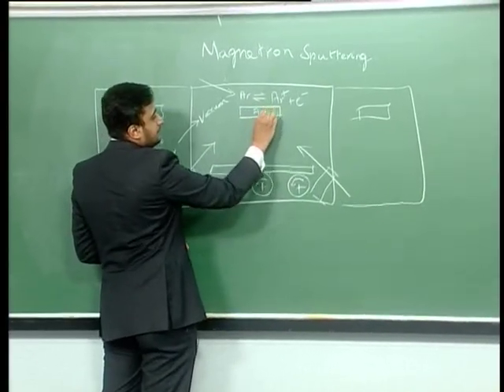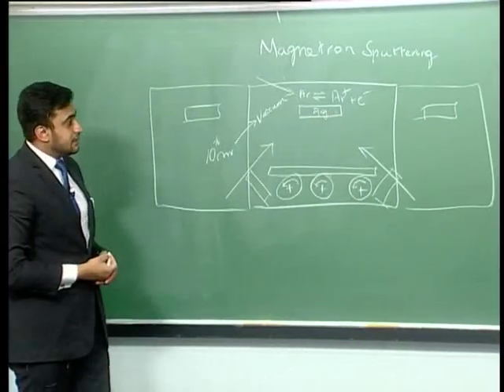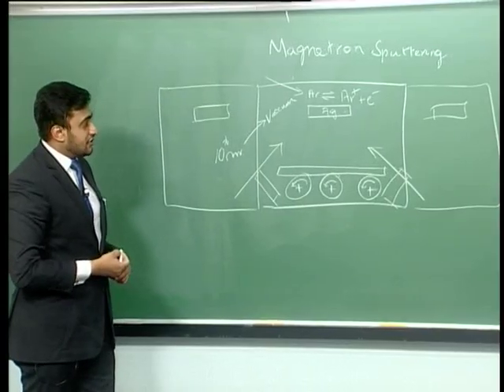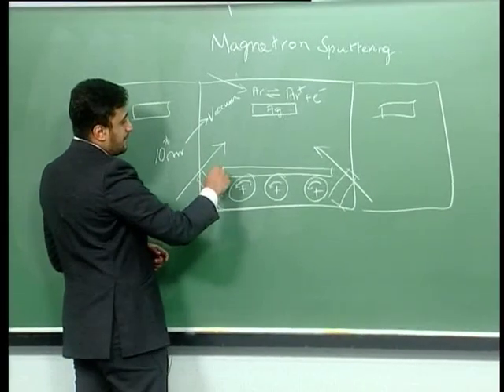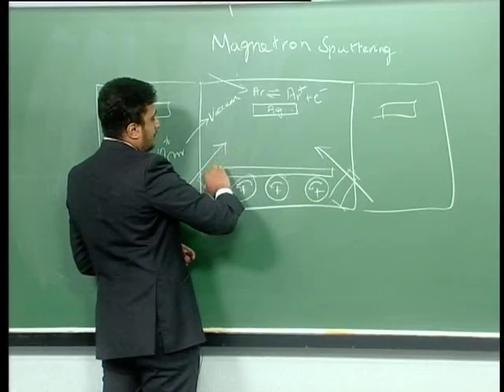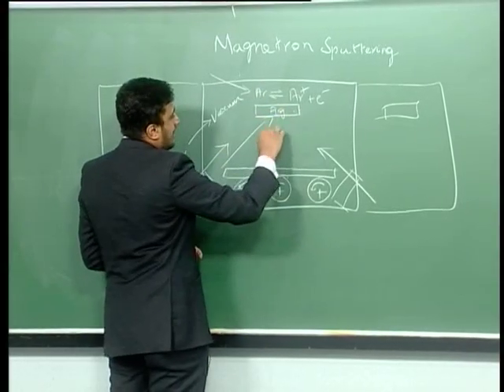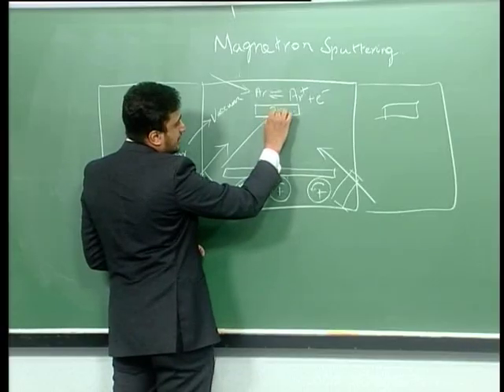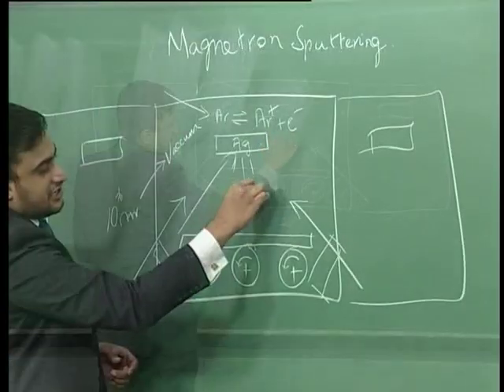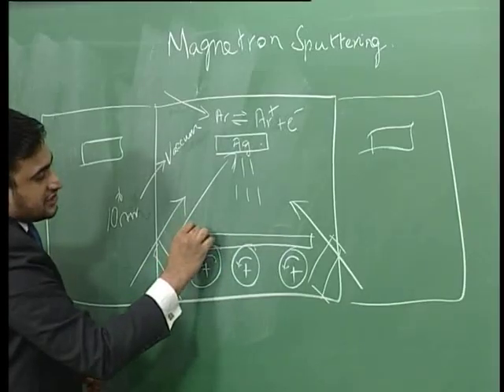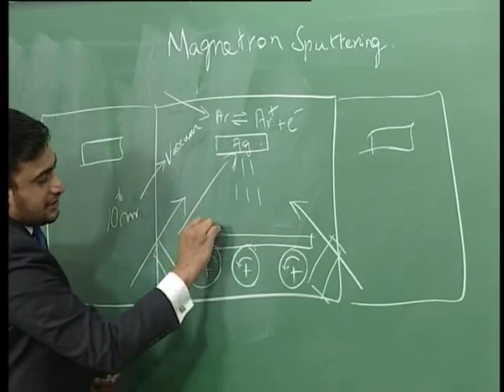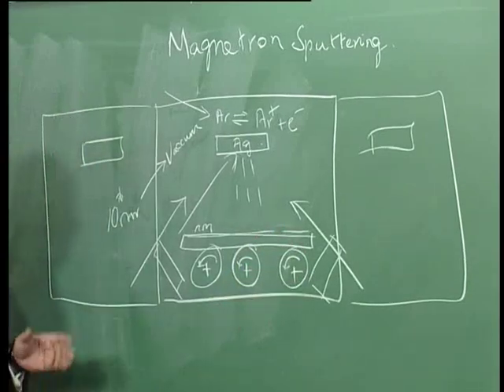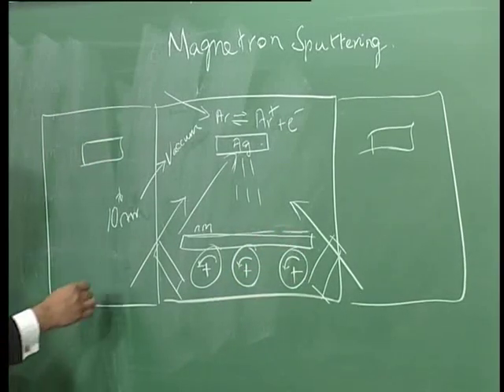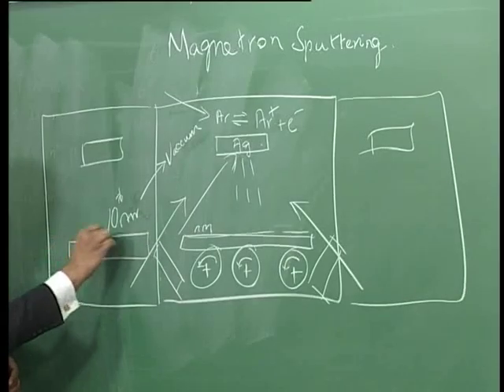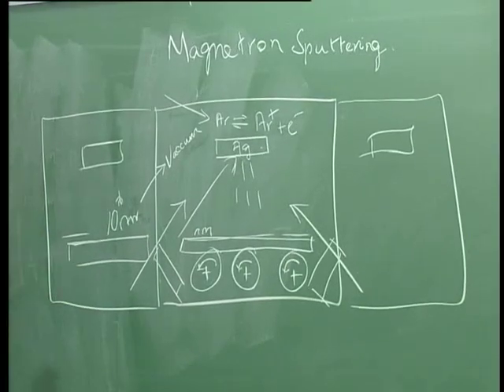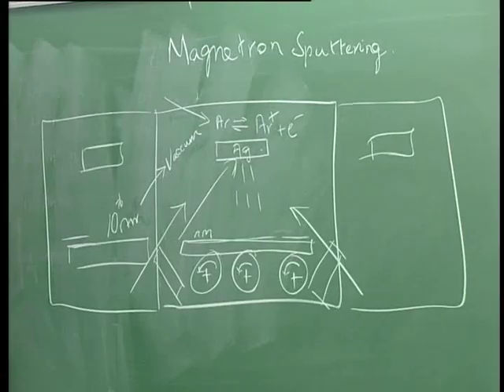Let's take, for example, the target material is silver. Silver creates a low emissive coating on the glass. What happens within the chamber is the electromagnetic directs the argon towards the target material, causing the target material to sputter on the glass. Now this creates a nanometric coating on the glass. Because you have 42 such chambers, this coating can be engineered to give you any type of performance. Let's look at a sample coating now.